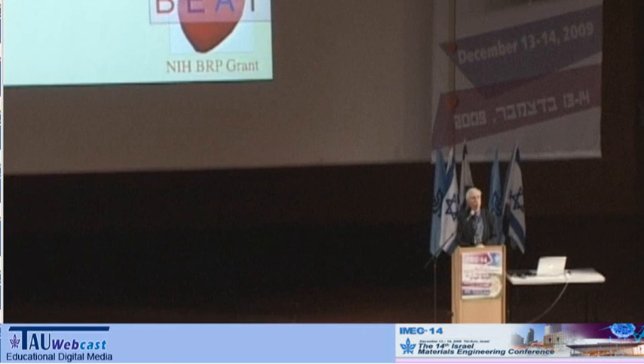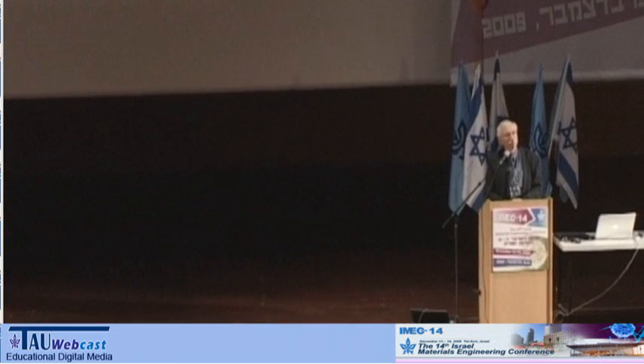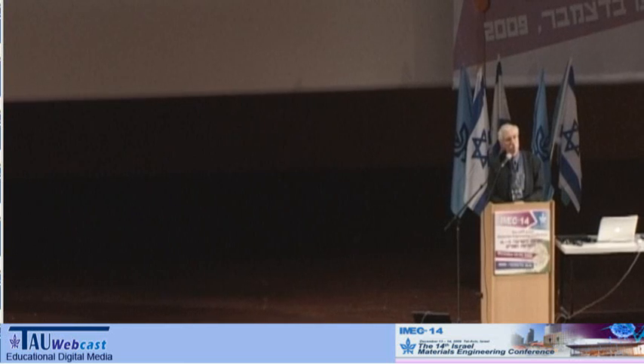A very exciting talk. I have one question. You show that these microspheres, when chosen to be 35 microns, work better than the 200 micron size spheres. Now, did you ever try some polydisperse distribution to check several different exact polydisperse distributions to see which one works better? Because in biology, usually you have polydispersed things, or in many cases you do. So maybe if you add smaller pores to the 35 microns, you can do even better than that.